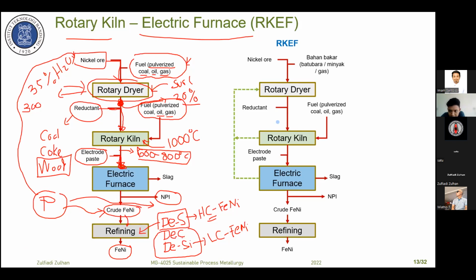If we do the decarbonization, and also we do the... for sure, we remove also silicon. In that case, we can also remove phosphor. But if we produce only high carbon ferronickel, we should control the phosphor content in the ore, because the requirement